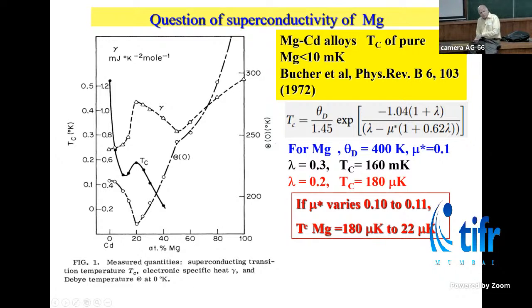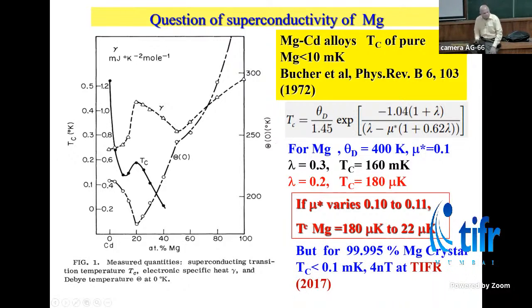We tried gold also down to 50 microkelvin. It never superconducted. There were many failures. Bismuth is one of the successes. Is that prediction ever reliable? It is not. So what we wanted to know was to set a lower limit for the magnesium. I'm just telling this because, all these predictions, even if we change mu star by this, if it changes that, I don't believe that theory so much. But then we need to prove experimentally that at least up to 100 microkelvin, we are sure that it is not superconducting.